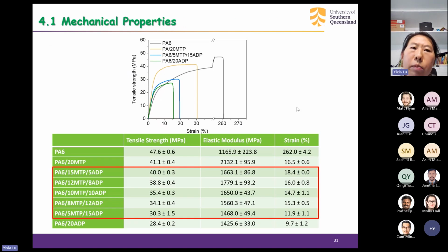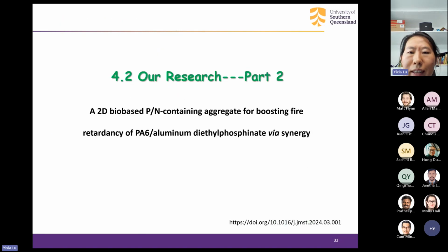Lastly, we investigated the mechanical properties. You can see here in this table, although the strain declined to a large extent, the tensile strength declined to a minor extent, and the elastic modulus increased. So we can conclude that the addition of MTP into ADP-based PA6 composites increased the mechanical property. So the second research is a bio-based PN containing compound.